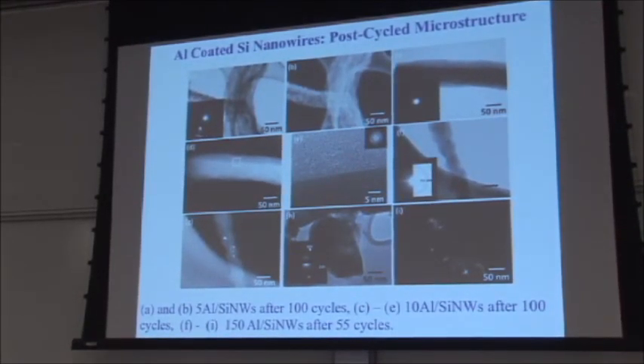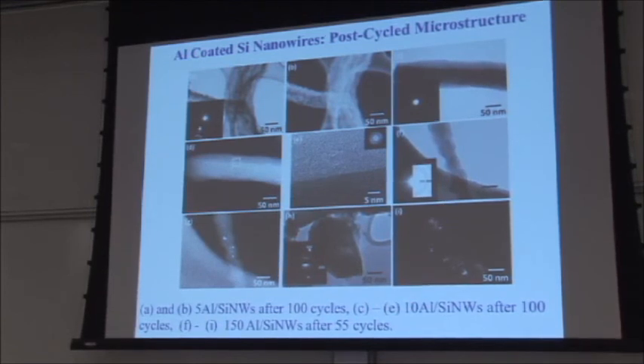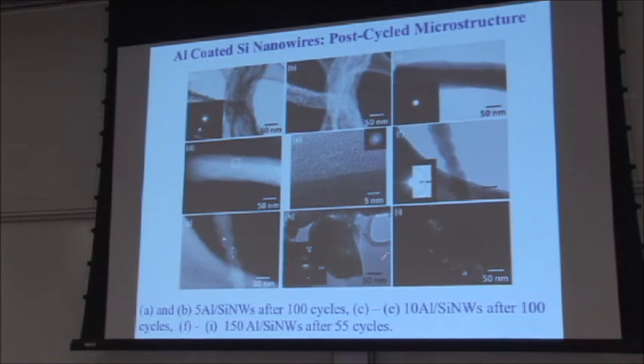It's virtually impossible to look at lithiated microstructures in a microscope without an infinite number of precautions in terms of destroying the sample. If you look at the really thick coatings, what you see is that the silicon nanowire underneath the aluminum is not intact. It kind of disintegrates. And the aluminum stays, but the two are in fact separated. So when you try to image it, you see the wire here, but you actually don't see the wire in the thicker coatings. And in fact, what you see is the aluminum literally just kind of peels off the silicon.